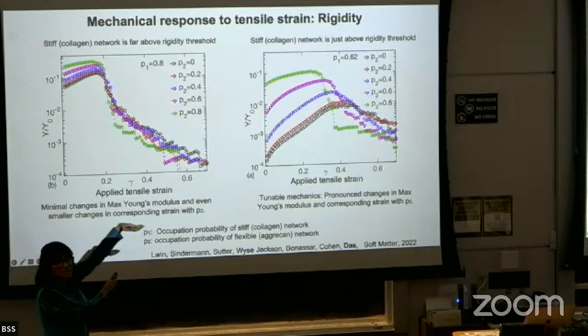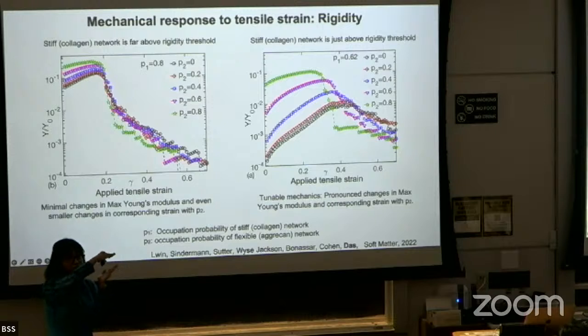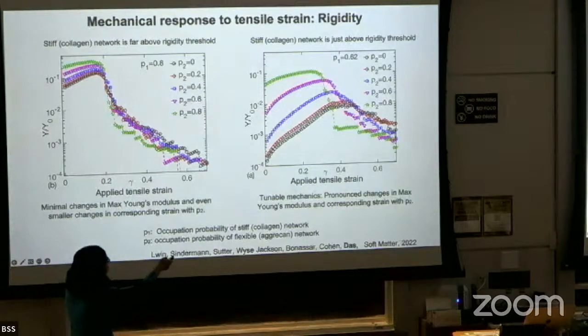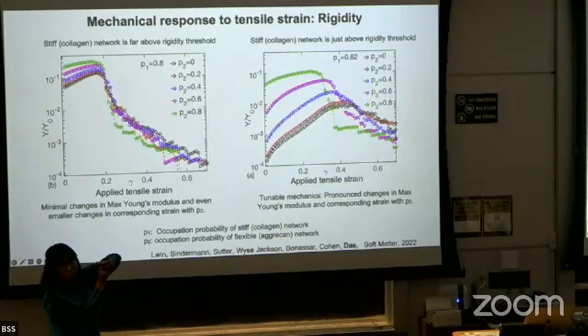But look at this. This is the situation when you're close to the bone and where the collagen network is just above its percolation threshold, right? So it's 0.62. The percolation threshold for this Kagome network situation with bending is 0.6. So this is just above the percolation threshold. And now as you increase the amount of aggrecan, you can see that the change in the stiffness is several orders of magnitude. And once again, you will see first some stiffening, then it will reach a peak, and then it will start softening, because when you have strained too much, bonds will start to break and buckle, etc.